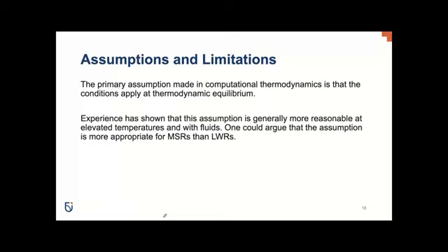And part of the reason for that is simply if you have a large, let's say, uranium dioxide pellet, the diffusion of particular components can be an important kinetic limiting factor. So having said that, one could argue that the assumption is more appropriate for molten salt reactors than it is for light water reactors.